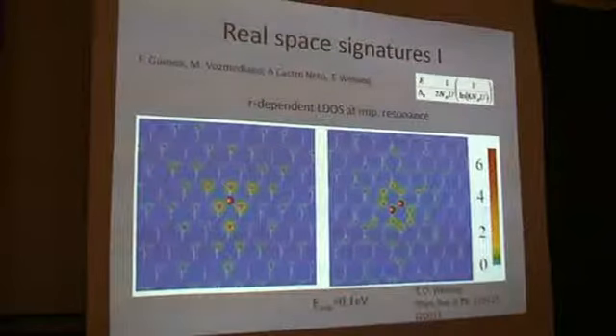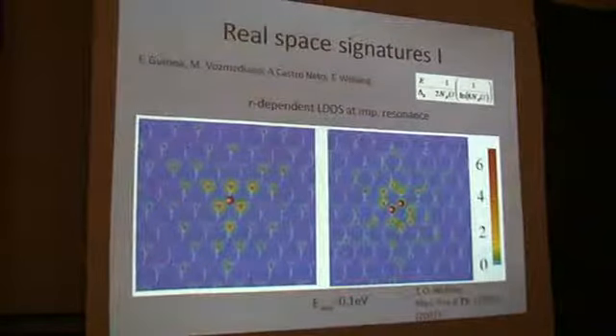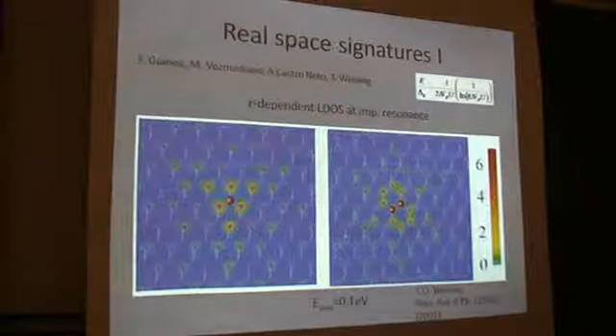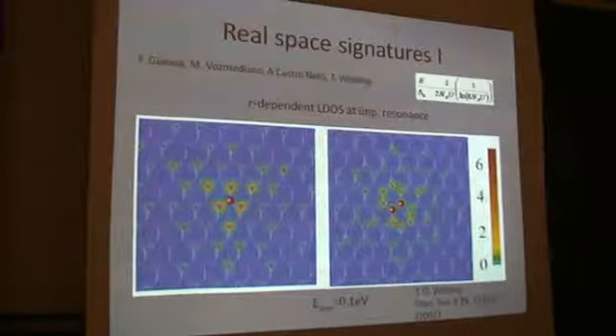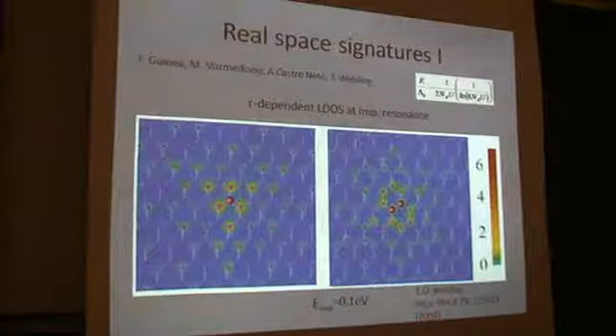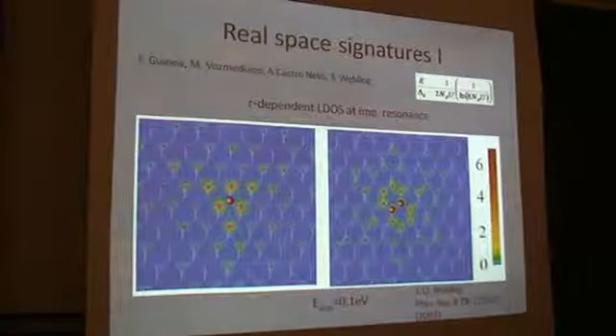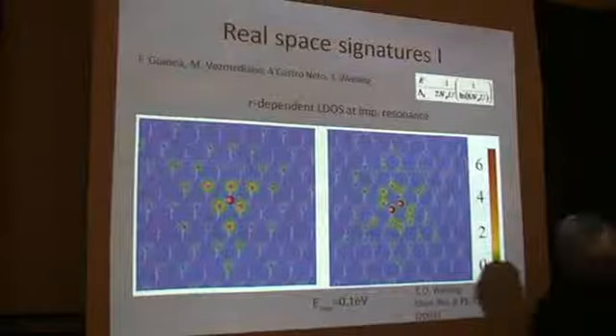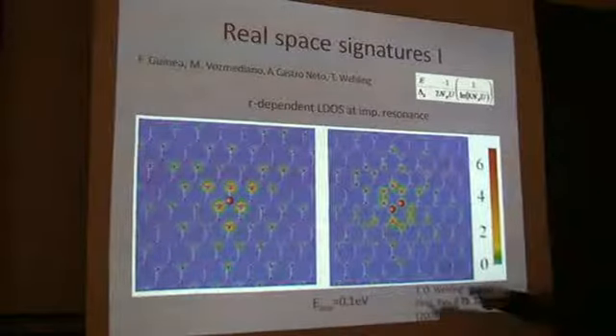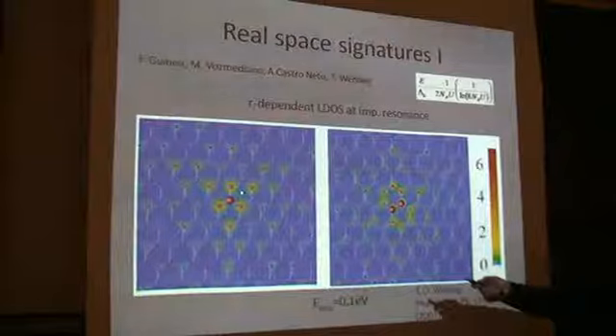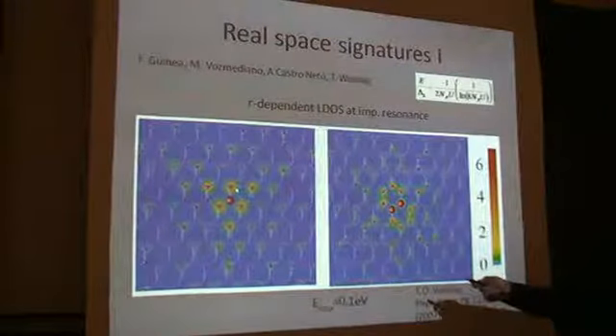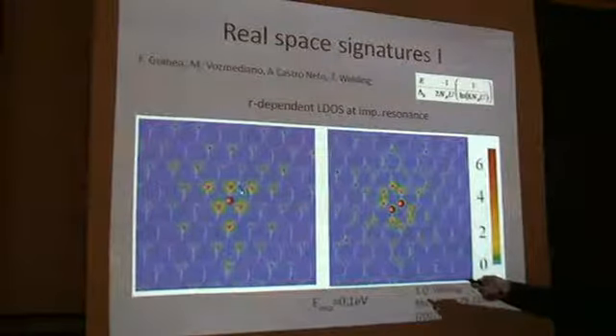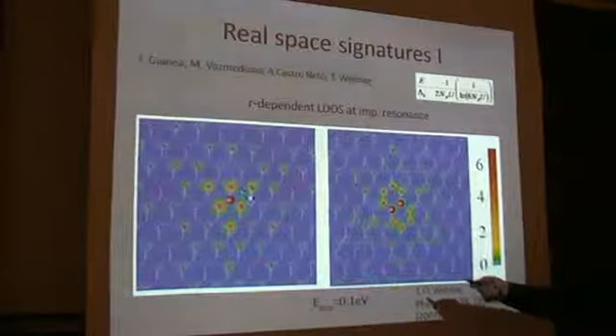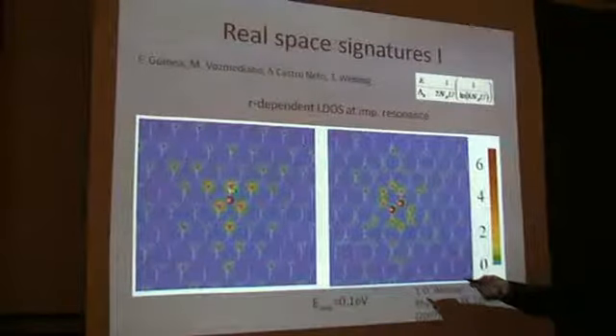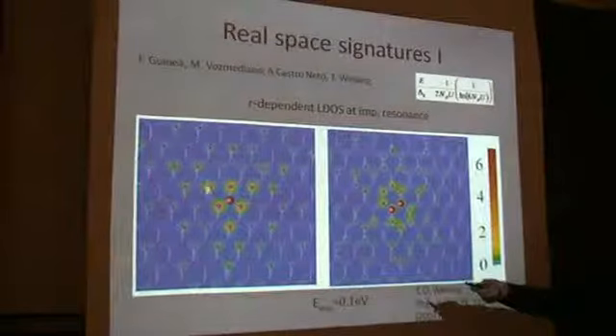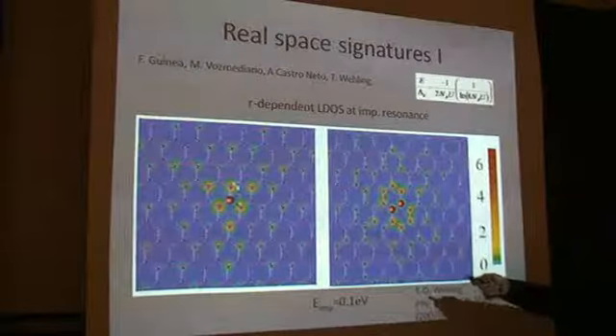Yeah, no, simple question here. Why do you consider that the impurity is on the site there? It could be in the center of the cell too, and then probably the profile will look completely different. Yeah, so we have answers for all of them. Not for all of them, I cannot do it for all of them, but we certainly looked at it. Just since you brought it up, you can put the impurity in the middle, in which case, especially for the Kondo effect, there is a very interesting Berry phase cancellation of contributions, which drastically modifies the Fano factors for the Kondo problem, compared to cobalt on copper. So we put it in the middle, we put it on the vertex, and we put it in the middle of the bond.